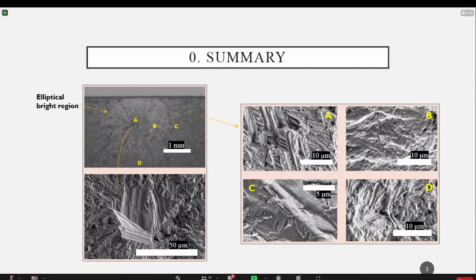and you can't see any striations there. And we hypothesize this is because the 2 faces of the crack are smashing each other, and that's promoting crack closure. Then as you go to the limit of this bright region, you start to see progressively more and more striations, which you can see in figure C. And last, as you go farther from this bright region, you just find the final fracture.